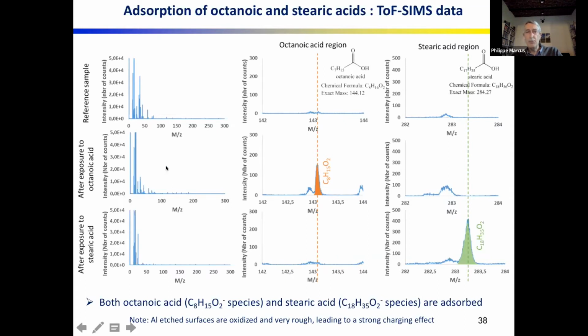Second row, that's after exposure to octanoic acid, and third row after exposure to stearic acid. And you see that, for example, if we look at the mass of octanoic acid, there is a clear signal after exposure to this inhibitor, but no signal in the other case. So we can conclude that there is indeed adsorption of octanoic acid, and this is in agreement with the XPS. Similarly, for the stearic acid, we observe a significant peak at the mass of stearic acid. So this confirms what we have observed by XPS.